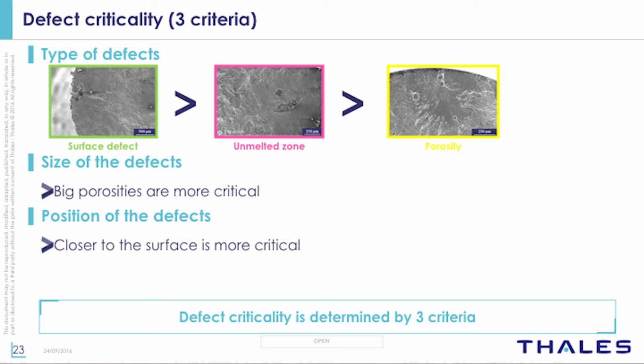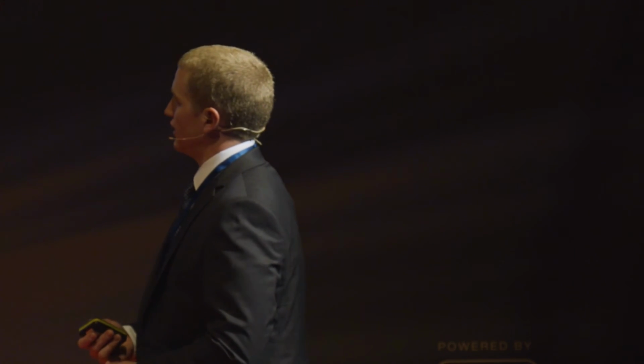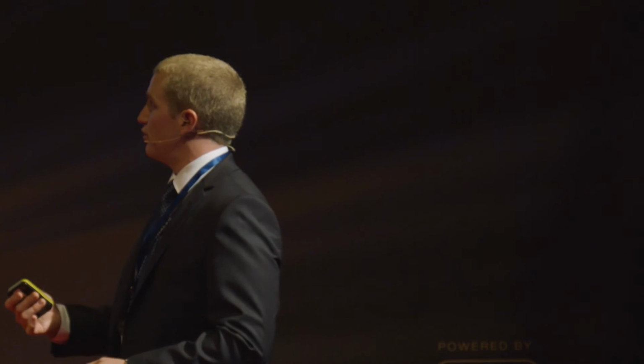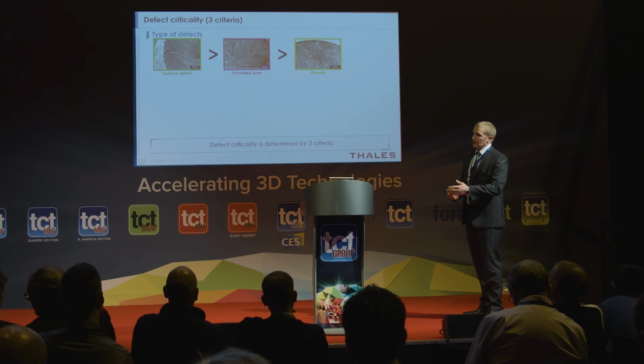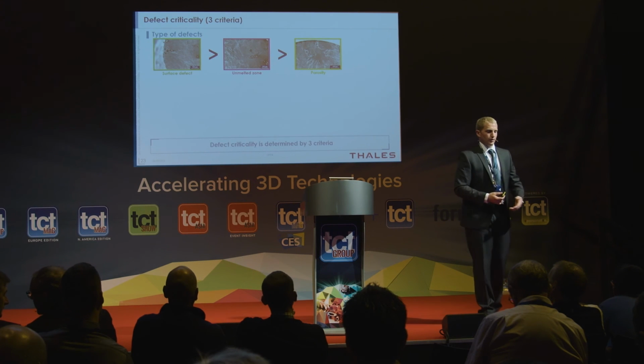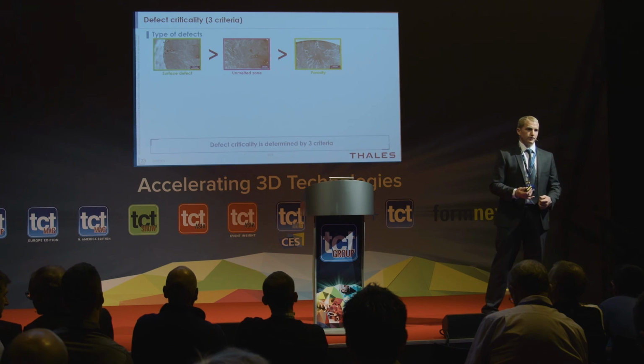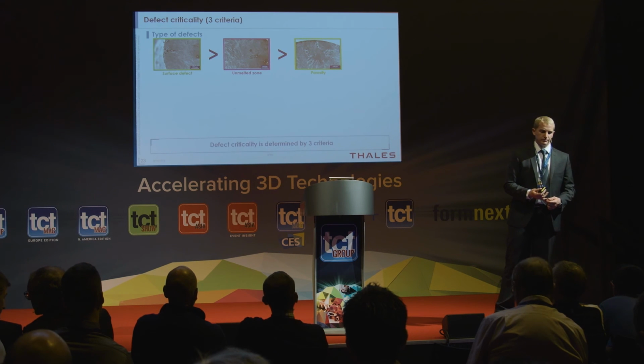If you know you've got an area that's critical to the strength of your part, you could look at polishing or machining the surface in that area to remove these. Then the next failure tends to be unmelted zones or unmelted areas of powder within the parts, and then porosities as well.